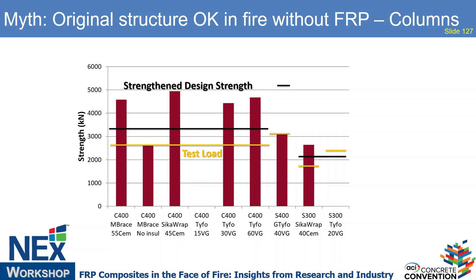of those column tests. And it shows some of the strength and design strength. And then we have the failures that we actually achieved, the loads that we actually had to apply to achieve it. And you can see even after fire exposure, in most of the cases, they well exceeded the strength and design strength. But we did have a couple of the columns where we didn't, so this one here, where we actually provided no insulation whatsoever. I think, Will, that was something you really wanted to investigate for those tests. And then it did, they performed quite well.